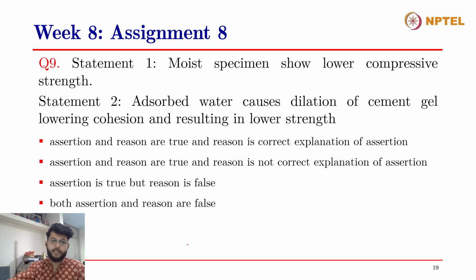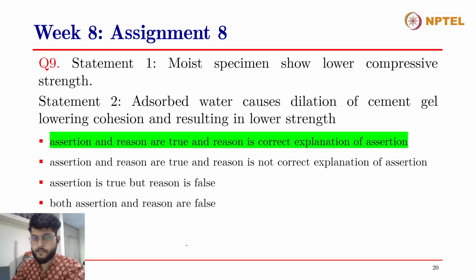All right. So the correct answer is the assertion is true, the reason is true, and the reason is also the correct explanation of the assertion. So yes, moist specimens show a lower compressive strength, and that is due to the fact that when you are ponding the specimens or curing them in a curing tank, you have filled all the voids, the capillary pores, the gel pores, and everything is filled with water from the external source, right? And the adsorbed water on the CSH gel causes a dilation of the cement gel. Dilation means that it kind of expands, or it makes the particles go farther away. So it dilates the inside of the cement gel, and therefore it lowers the cohesion between the solid particles or the solid hydrates.